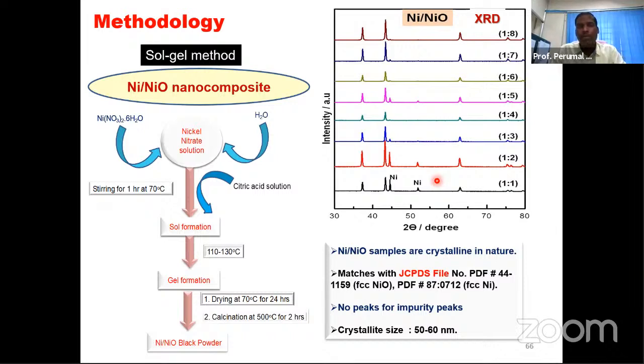Like this, if it is gold or silver, you can also characterize alloys. Vegard's law you can use for metallic alloys. The lattice parameter you can estimate. For any crystal system, there is a relation between the lattice constant and the interplanar spacing, d spacing. So you can estimate the lattice constant and plot lattice constant versus composition. If it follows linearity, it is known as Vegard's law, and you can predict the composition of the alloy. So you can know what components are present in a composite or a mixture, and distinguish an alloy from a mixture using X-ray diffraction.